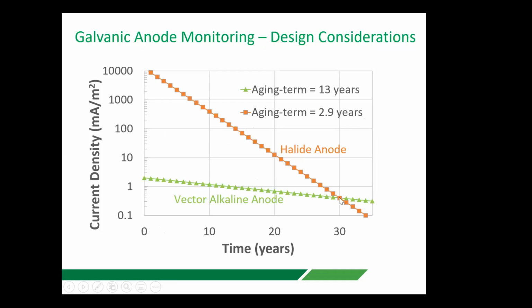And just to show it in a slightly different way, if our objective is to maintain a current density of 0.4 after 30 years, as I said, we need to start at around 2 milliamps per meter squared for the alkaline anodes, but well over 10,000 for the halide activated. That obviously is an impossibility.